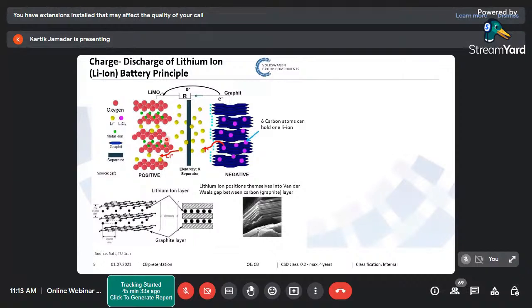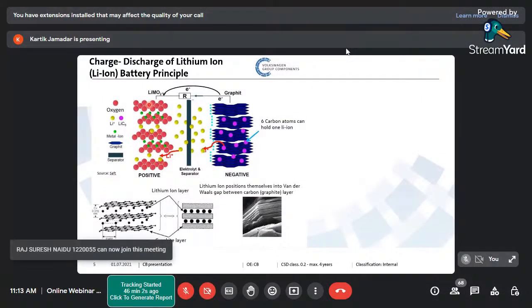When we are talking about the NMC cell, nickel manganese cobalt, which is practically used in the automobile industry, instead of using the metal oxide I just mentioned, they are using nickel, manganese, and cobalt in different proportions as a holder for oxygen. When we talk of the LFP cell, lithium iron phosphate, iron phosphate is the cathode material used to hold the oxygen. When we are talking about LTO, lithium titanate, instead of graphite we have a titanium oxide which is holding the lithium. So the principle is the same. The only thing we are changing is the anode or cathode.